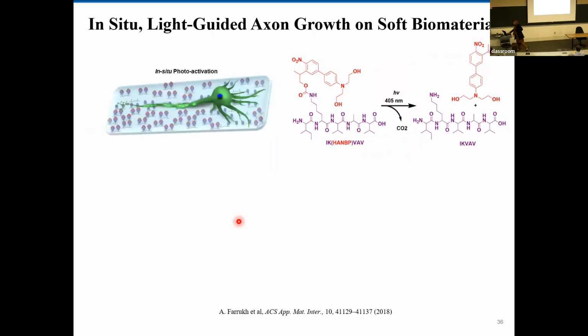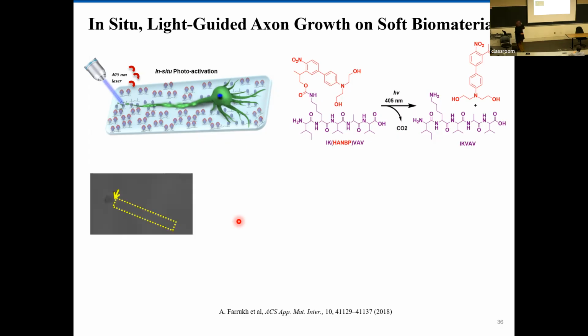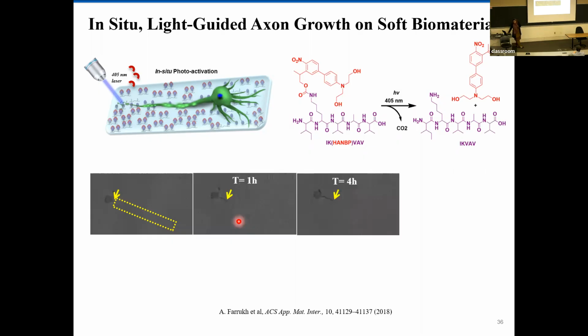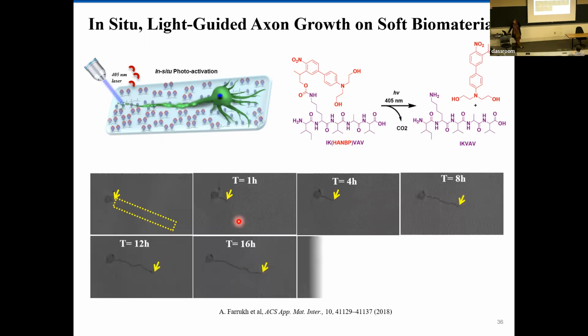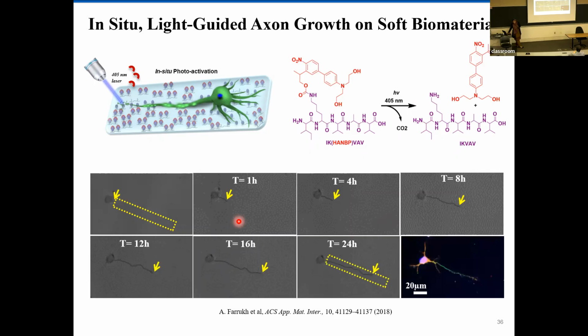In the next part, we wanted to do in situ activation, which means we uncage the peptide in the presence of cells, and then see if we can control the growth and direction of the neurite. So this is one cell, this is how a neuron looks before growth, just a small circle. I shine the light in front of it. This is a 100 micrometer irradiated area, and this only takes 10 seconds using a microscope. Then the light is shone, and the neurite starts to grow. Generally it takes 24 hours to grow, and it grows only in the area where we shine the light.